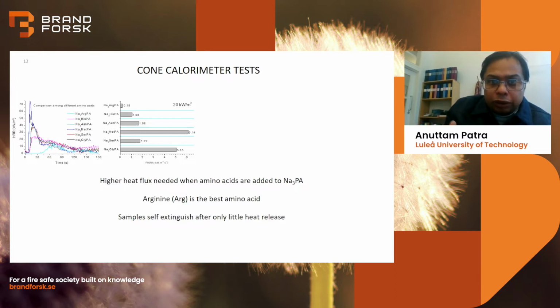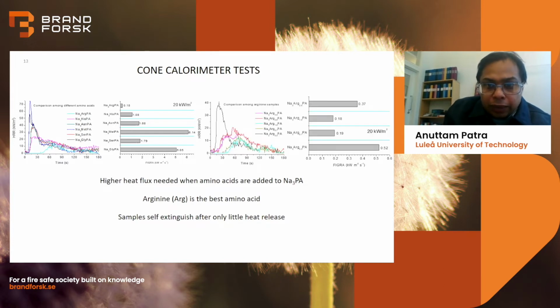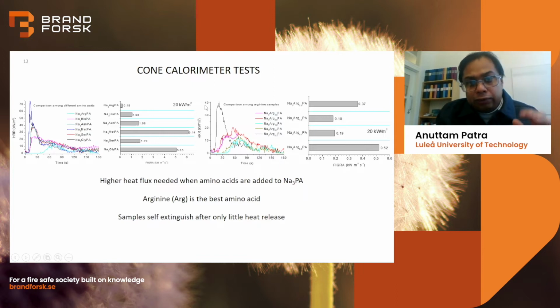What is the ratio between phytic acid and arginine to get the best result? When we put very little, 0.3 mole of arginine, we already started seeing very nice flame retardant behavior. It can withstand 20 kilowatt. Without arginine, of course, as I told, we cannot put this high heat flux. It will burn, it caught fire immediately.